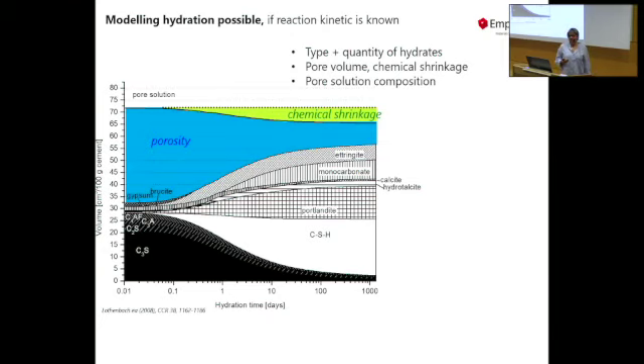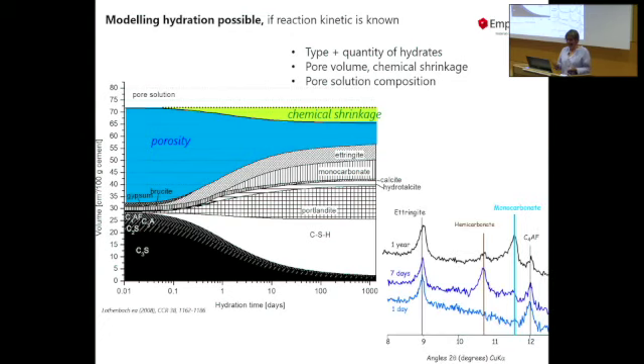So if the Portland cement hydrates, you have less and less water, which is plotted here in blue. You also have something which we call chemical shrinkage. And chemical shrinkage is just due to the effect that bound water has a lower volume than free water. And that's what you can measure if you do chemical shrinkage measurement. And the third thing you can see, the solid volume is increasing, which is the reason why we start to have more and more strength in our system. And this picture you've seen before, it's basically the picture of that hydrating cement, where we first make ettringite, and after a day or two we start to make monocarbonate or the AFM phases.